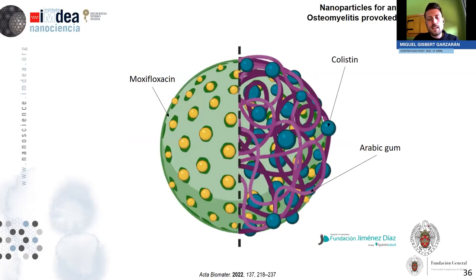Okay, so in the first case, for the treatment of osteomyelitis induced by E. coli, we designed this system. Basically, we have MCM41 mesoporous silica nanoparticles loaded with an antibiotic, which is moxifloxacin. And then the surface was functionalized with Arabic gum and colistin, which is another antibiotic. So let me tell you, first of all, that the original idea was to engineer a gatekeeper with the Arabic gum. But for that, we had to use a lot of Arabic gum.